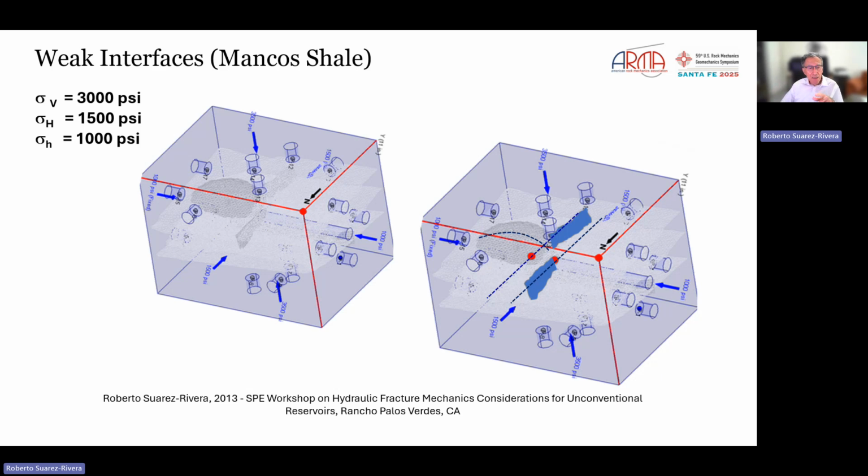And so we are applying a uniform vertical stress on this block, but by the time the stress is propagating through the system it is no longer uniform. And that complexity in the stress distribution is promoting the delamination of a fracture along the border of this concretion. So that's one.